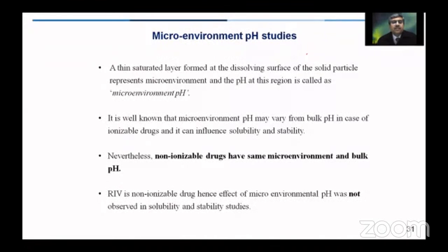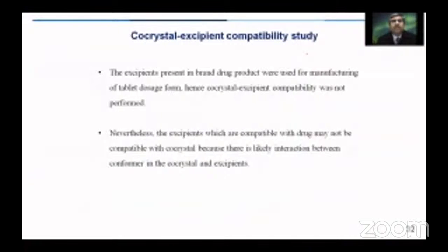The microenvironment pH studies were carried out because they can affect both the solubility behavior as well as the stability behavior of a compound. A thin saturated layer of water is formed at the dissolving surface of the solid particle, and this represents the microenvironment, and the pH at this region is called the microenvironment pH. Rivaroxaban is a non-ionizable drug and has the same microenvironment and bulk pH. So since it is a non-ionizable drug, the effect of microenvironment pH was not observed in solubility and the stability studies. So this again came out to be a non-critical pre-formulation parameter for rivaroxaban co-crystals.